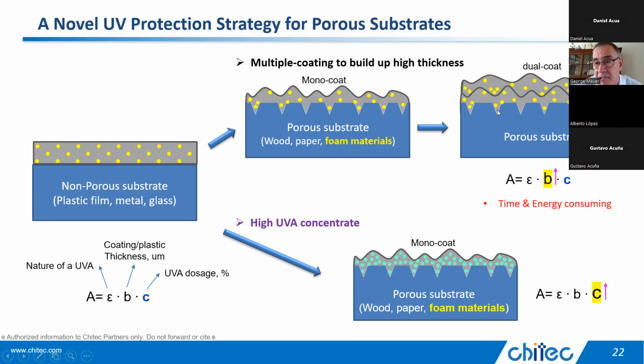So the concept here is that this substrate is sensitive to UV light, and you want to get UV protection above it. This just gives you a way to get a lot more concentrated UV absorber into your film. And so you can use less coating. For instance, in this case, you might have 1 mil of coating in order to absorb all the light, maybe 2 mils. And here you might need 2 or even 3 times as much coating to absorb all the light. Does that help?